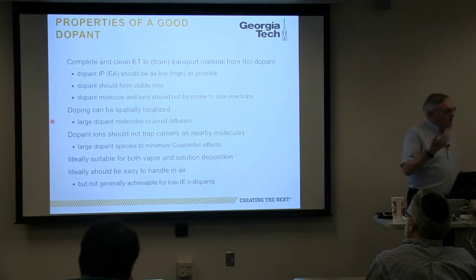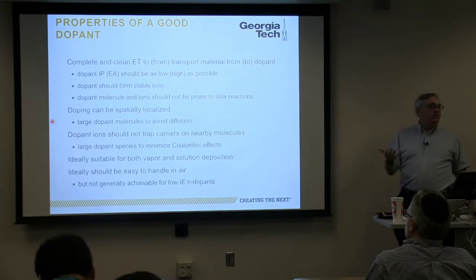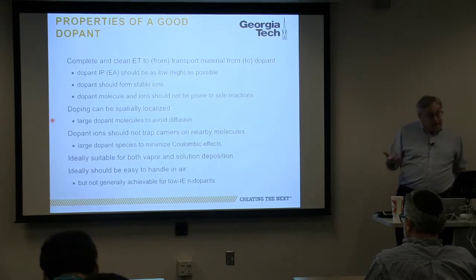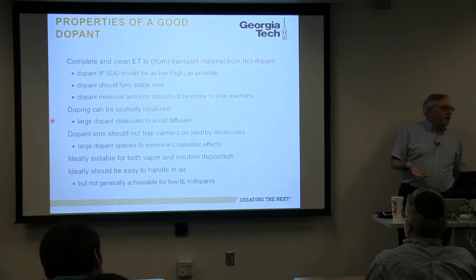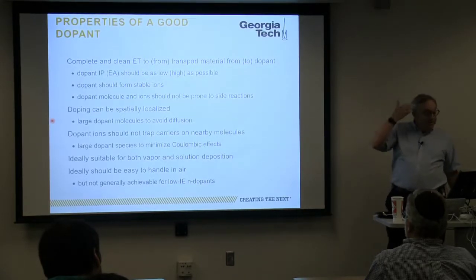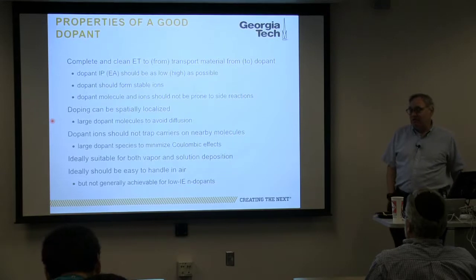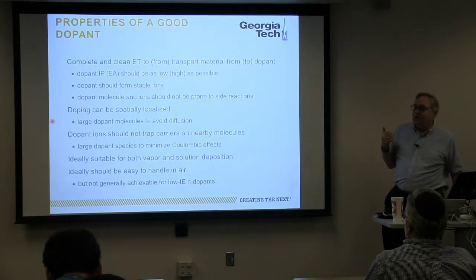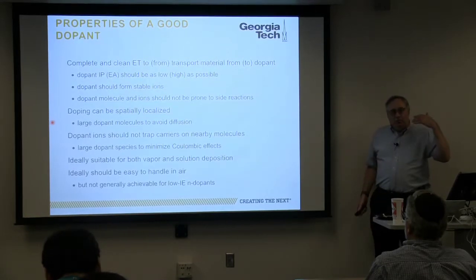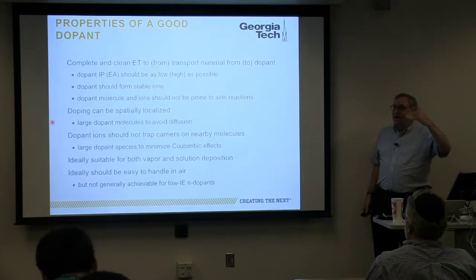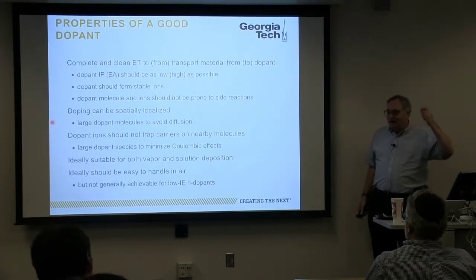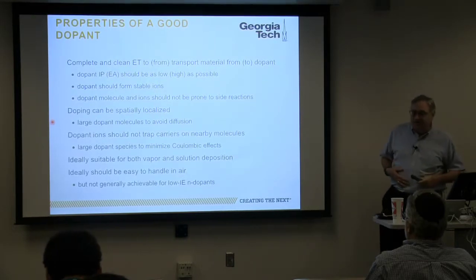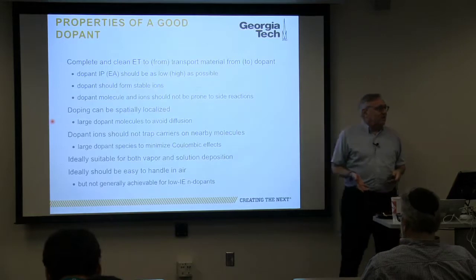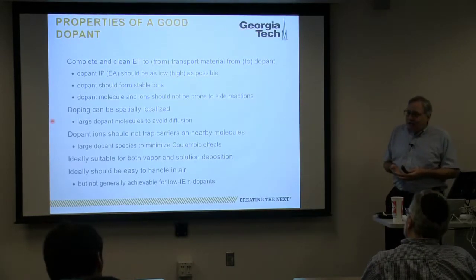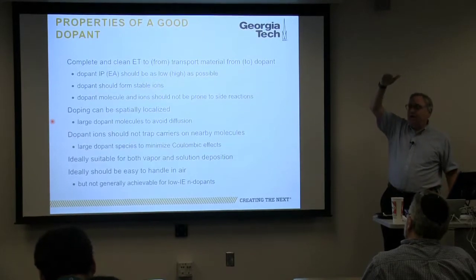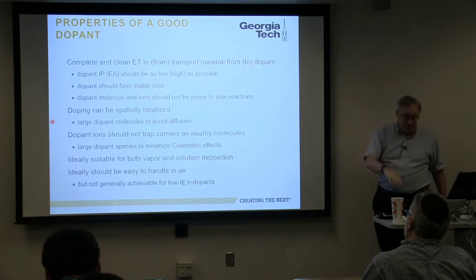So for p-dopants, things that are oxidants, in general, except for the most oxidizing of materials, that's relatively straightforward. Some materials will actually interact with the water in air and become reduced, and that can be problematic. For n-dopants, it turns out that that's a much more challenging situation. Because if you look at the materials that you want to dope, typically it will require something to dope them with a sufficiently low ionization energy that oxygen can oxidize the dopant, okay? And we set out for ourselves the challenge of identifying dopants that would be relatively stable in air and yet be able to dope things that are very, very difficult to dope, i.e. have very low electron affinities, okay?